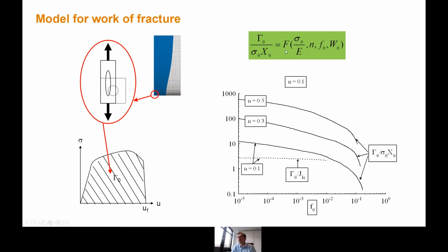And you see the symbolic equation on the top: the gamma zero, this energy per unit area to grow voids until failure, normalized by the distance between voids and normalized by yield stress, is a function of different parameters. F0 is the initial porosity, and W0 is the initial shape of the void. We calculated this parameter for different strain hardening exponents. We also compared the gamma zero to a J1C value that would be obtained in pure plane strain. If you trust the model, and there are many assumptions so we have to be careful, the ratio of the two would be a factor 3. So the gamma zero, if everything is correct here, would be 3 times the J1C.